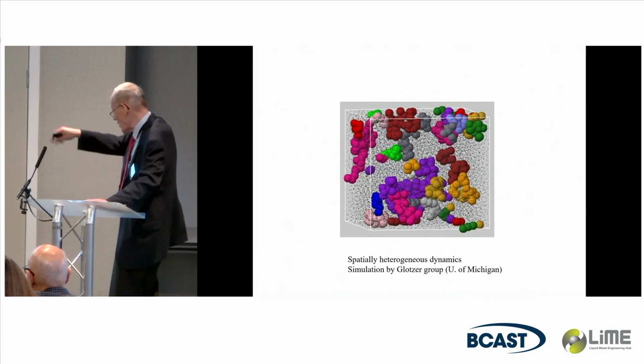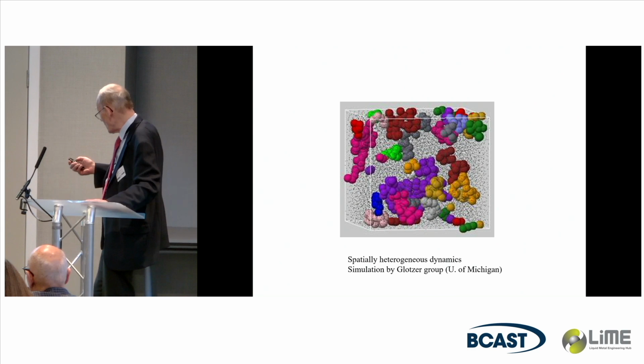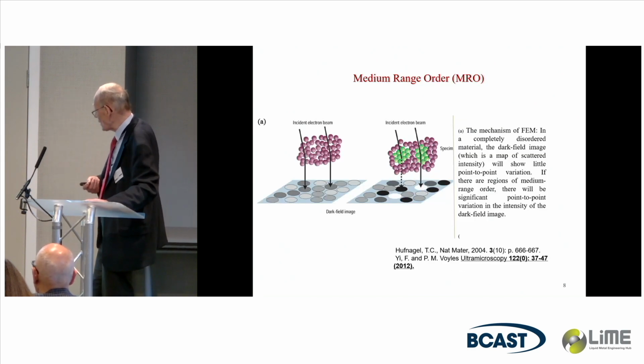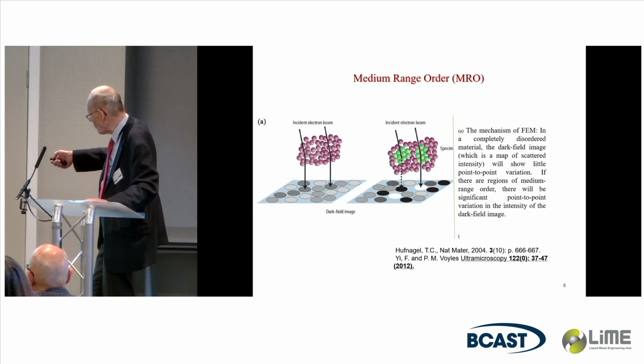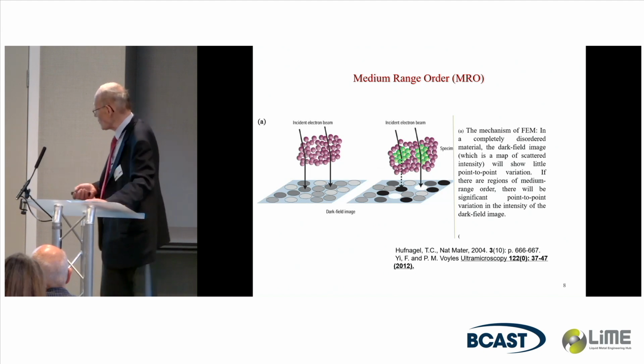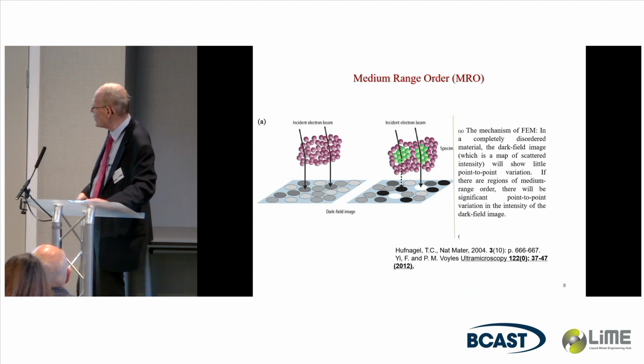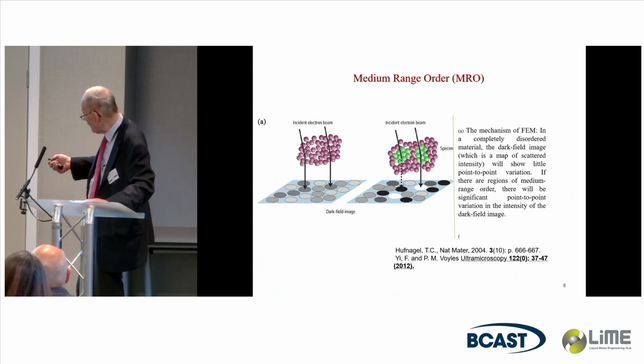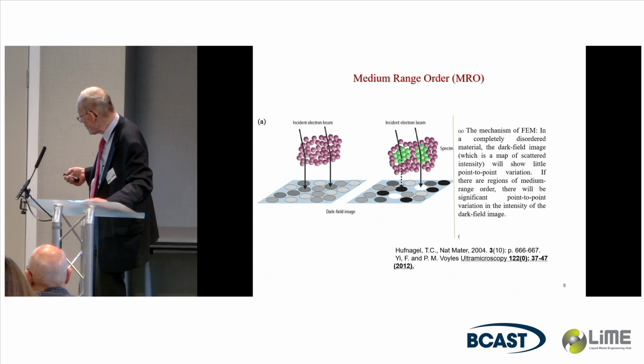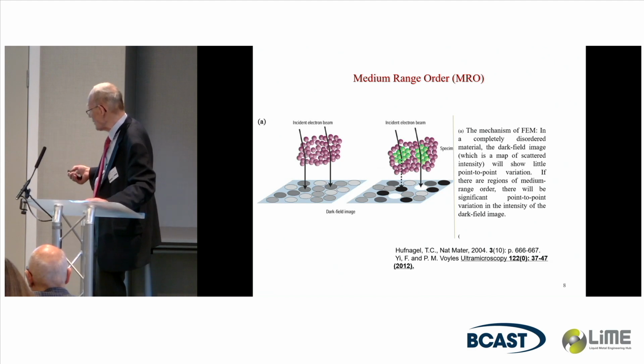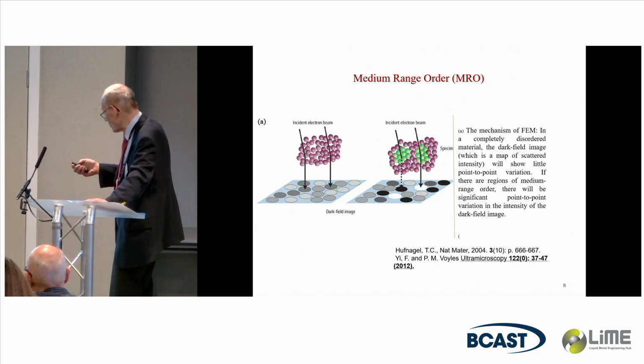This is a computer simulation from Sharon Glotzer. But we have seen them in actual practice, with a colleague of mine, Paul Voyles. We use fluctuation electron microscopy. If you have a spatially homogeneous material, then the fluctuation electron microscope image is mostly uniform in its intensity in the dark field image. But if it's spatially heterogeneous, you have groupings of atoms that are close together, then you're going to get intensity variations. And by analyzing the intensity variations, you can back out what the type of clustering is and the density and numbers, the size and number density.